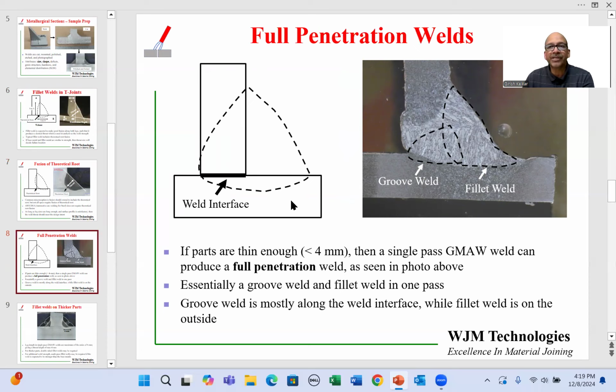Here again, I'm showing you a schematic on the left. It's again a T-junction. And I'm showing you a weld cross-section on the right, where, given the fact that the base metals are quite thin, with the right welding conditions you can make a weld which is deep enough that you are actually getting penetration all the way along the weld interface. So that is called a full penetration weld.